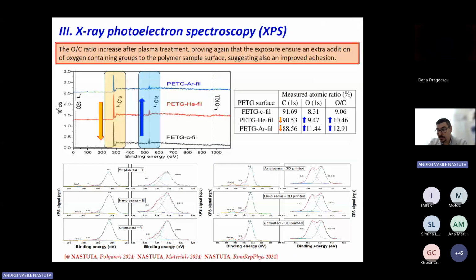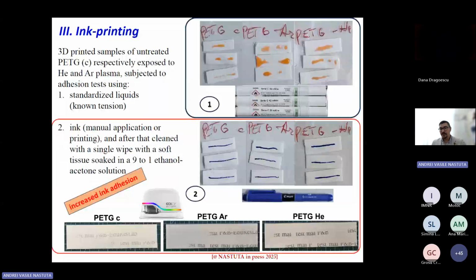To back up the oxidation processes of the surface after the plasma treatment, we also did some XPS measurements, and we saw that the oxygen content is increasing after the plasma treatment. This was no surprise, but it was a scientific verification of the things that we can do with the plasma to the surface.